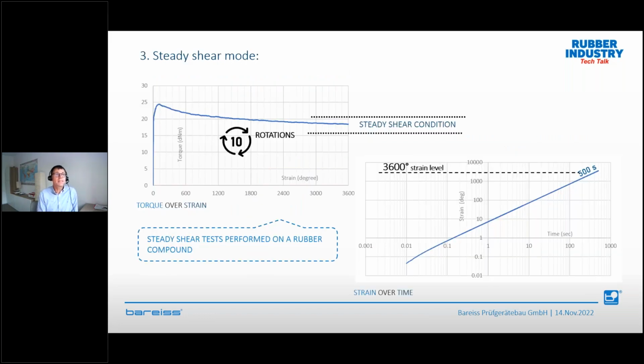The next one is the steady shear mode. So what does it mean, steady shear? You see here something like rotation. So what we discussed all the time until now, on a frequency sweep, an isothermal test, a non-isothermal test, when we're talking about strain sweep, we always make an oscillation, plus minus a degree of arc. But here we now start and make a rotation of the lower die. So remember, a little bit like Mooney when the rotor is rotating. And that is what we are doing now with the RPA.